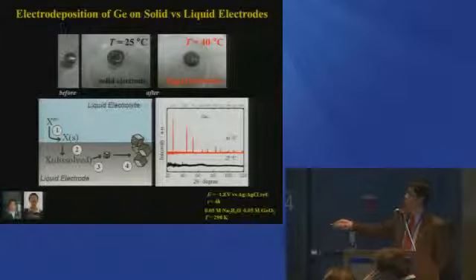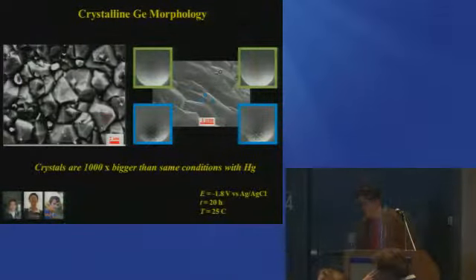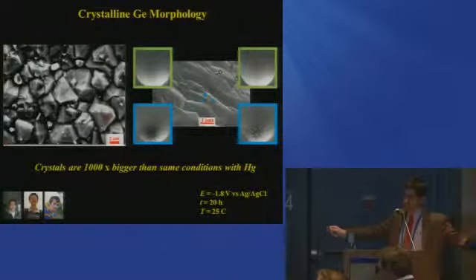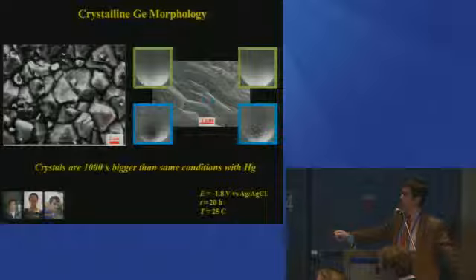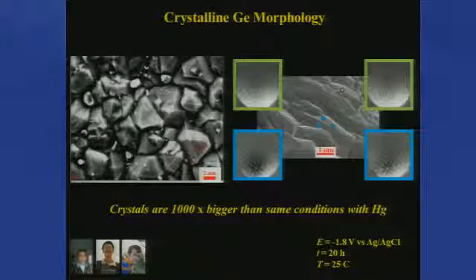And so these are the results that we get. When we do this electrodeposition with hot molten gallium, hot being 40 degrees Celsius, we always get crystalline germanium as our product. When we do it with solid gallium, we always get material with very little or no detectable crystallinity. That lends credence to this idea of really doing electrochemical crystal growth. Under the exact same conditions where we were extruding out nanowires with mercury, gallium doesn't give us nanowires. What we end up getting are large crystalline grains of germanium. These crystal grain sizes end up being about 1,000 times bigger.